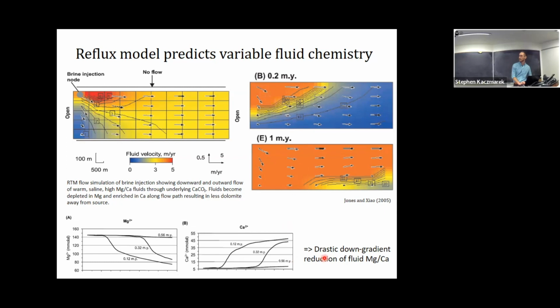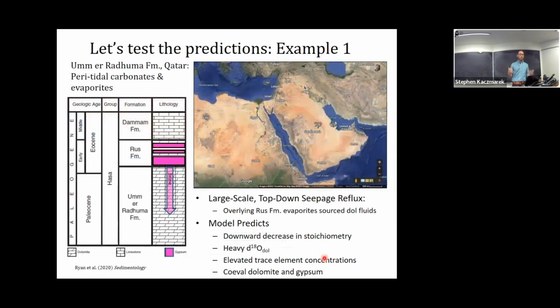So for every parcel of water down gradient, the magnesium calcium ratio of those fluids goes down and down and down, and it's losing dolomitizing power along that gradient. The cool thing is that's one of our key chemical parameters that changes dolomite stoichiometry, so we can look at spatial changes in dolomite stoichiometry to test this model.